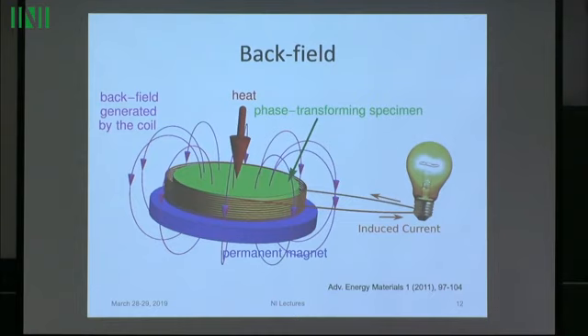And this modification is very important because, remember, the magnetic field affects the transformation temperature of the specimen. So the presence of the back field has the effect of raising the transformation temperature on heating and lowering the transformation temperature on cooling. And that's absolutely critical because we know from the first lecture, from the efficiency estimate, that if the minimum temperature and the maximum temperature are the same, then we don't generate any work. We don't generate any electricity.